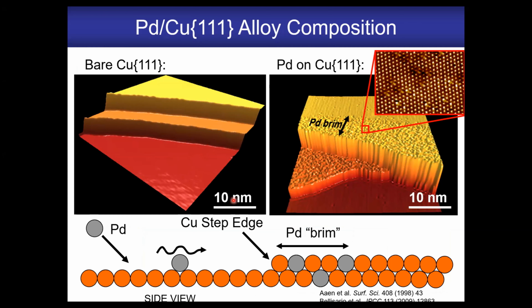And then we basically heat up samples of palladium, for example, so that you evaporate small amounts of palladium; the atoms fly through the vacuum, land on the copper surface, and you can see in the STM image after the alloying has been done that around the monatomic step edges you see all this rumpling. But if you zoom in with atomic resolution, and again we've only put 1% palladium into the copper surface, we see some single atoms in the surface and some single atoms underneath the surface. So the ones in the surface layer are slightly brighter here, and the ones underneath are slightly darker here.